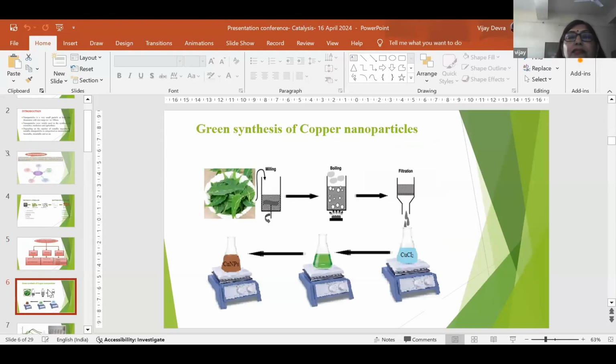Here I am discussing the green synthesis of copper nanoparticles, in which we use plant leaves, particularly Azadirachta indica, commonly known as neem. First we collect the neem leaves, then after milling and boiling, we prepare the neem leaf extract, which is added into the particular salt. Here I am discussing the preparation of the copper nanoparticle. Then we add the copper salt. As time passes, the color of the suspension changes from green to dark brown, which confirms the formation of the copper nanoparticles.